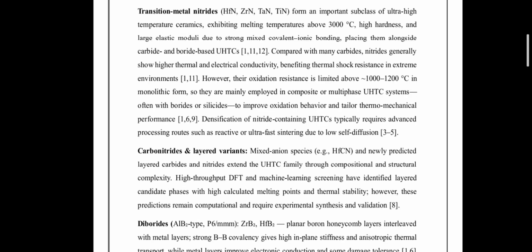Next are the carbonitrides and emerging mixed anion systems like hafnium carbonitride, which allow tuning of bonding and defect chemistry. High throughput DFT and machine learning studies have predicted layered carbide and nitride phases with high thermal stability. However, most of these remain computational predictions and require experimental validation.